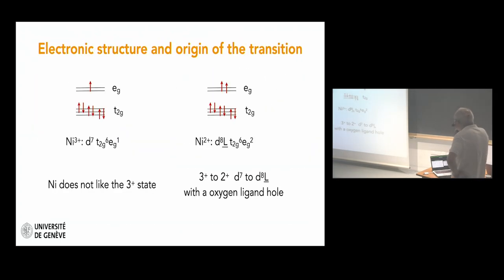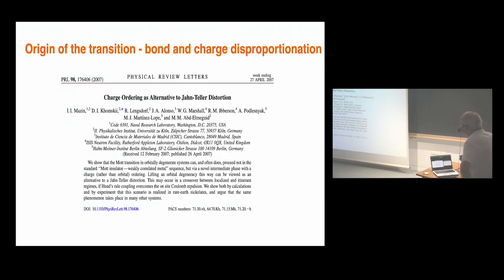Okay. Let me move now and discuss the electronic structure and the origin of the transition. So in our nickelates, nickel is 3+, d7 low spin. So remembering what we said about the t2g and eg, we are in this situation with full t2g orbitals and one electron in the eg with a degenerate state. As Andrea mentioned yesterday, we can also have a picture where the system is d8L with a ligand hole with the oxygen.